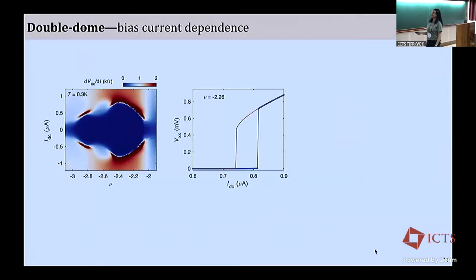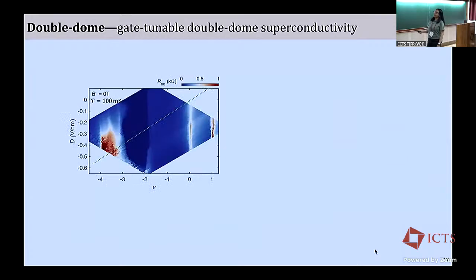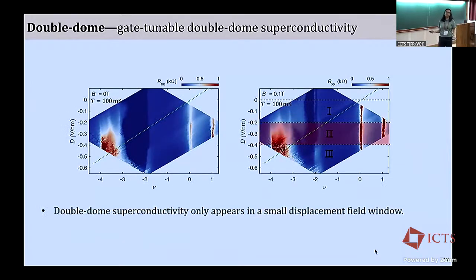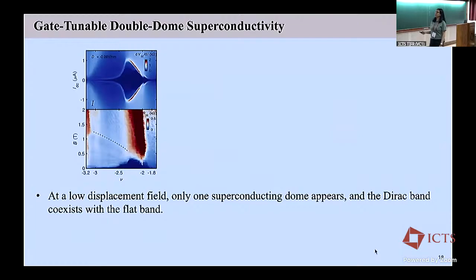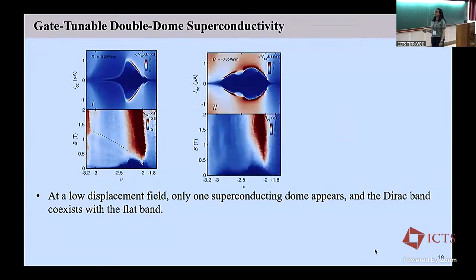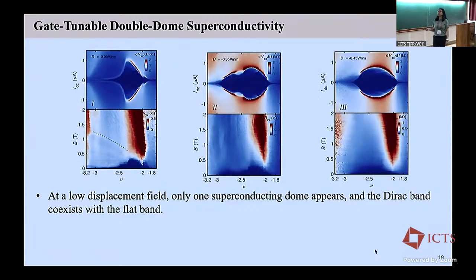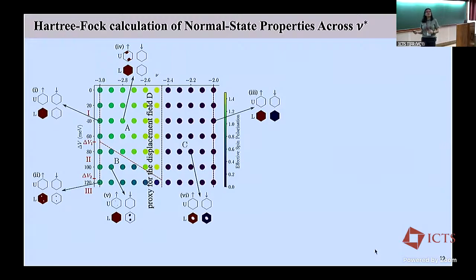Sorry for going back. Basically I'm trying to show what we are tuning after all. It's the band structure, right? At low displacement field, we see one dome, and you can also see the Dirac electrons here. Then in between, in this displacement field range, we see this double dome. I don't think I can see the Dirac clearly, but definitely there is no more Dirac left. And you see again one-dome superconductivity. So that's what we have seen experimentally. And then, of course, we went to Sid and Steve for their calculation. If you need more information, yes.